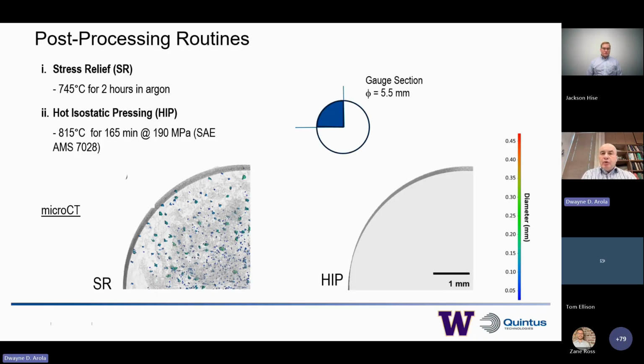So just to make sure I point out clearly, our program involves two different forms of heat treatment. One was a stress relief treatment, which was conducted, as you see, at 745 degrees Celsius for 2 hours. Another portion of that particular lot of metal produced by the partner was subjected to hot isostatic pressing. We could compare the properties that come from stress relief and hot isostatic pressing, and then understand how that contributes to variability. The HIP process was conducted, as Jackson pointed out, according to the AMS 7028 spec, which is this low temperature,